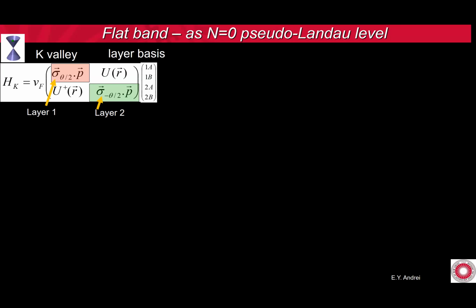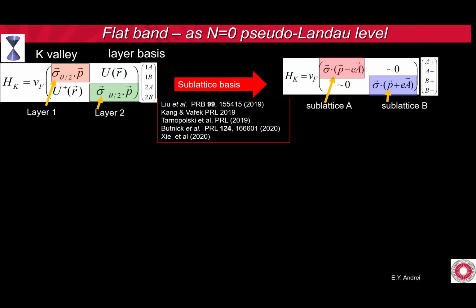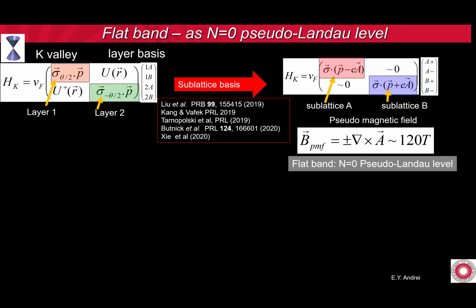But if you switch bases, if you go from the layer basis to the sublattice basis, this is what happens. So the top block is sublattice A, the bottom block is sublattice B. So now the Hamiltonian acquires a gauge field, which has opposite signs in the 2 sublattices, okay? So these are bonding and anti-bonding states in the A sublattice and the B sublattice. If you take the curl of this gauge field, of course, it's going to be very non-uniform, but at the center it is maximum, and it's of the order of 100 Tesla. Of course, it goes to zero at the edges of the moire.